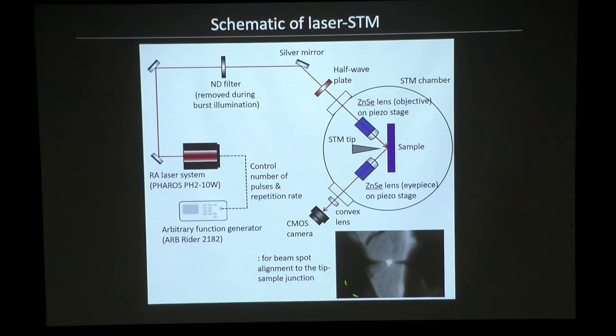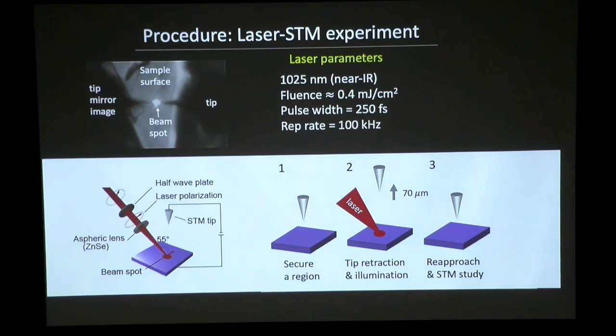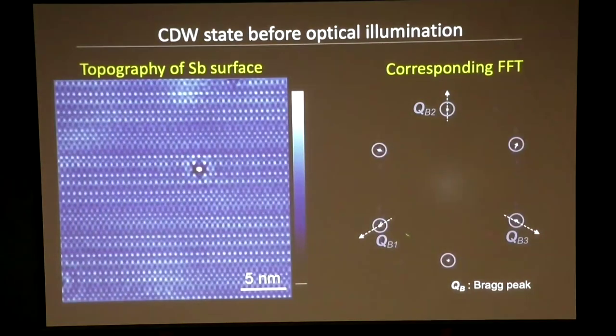So using this optics, we can position the tip right on top of the optical beam, which has a diameter of 10 microns. The way this experiment is done, there are many modes of operation, is that we secure a region, we retract the tip, shine light, and then we turn off the light. So the experiments were not done in the presence of light. We use the light to create a metastable or a sort of long-lived state. And then we turn off the light and then reapproach and do the measurements. OK, so this is a topography.